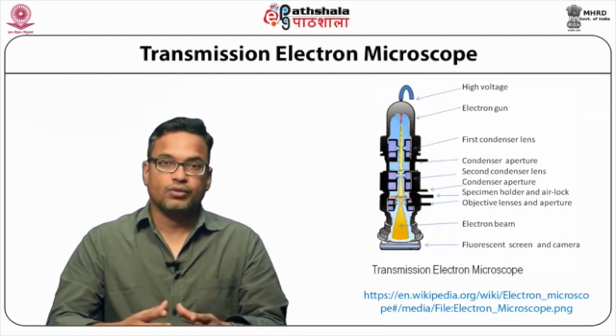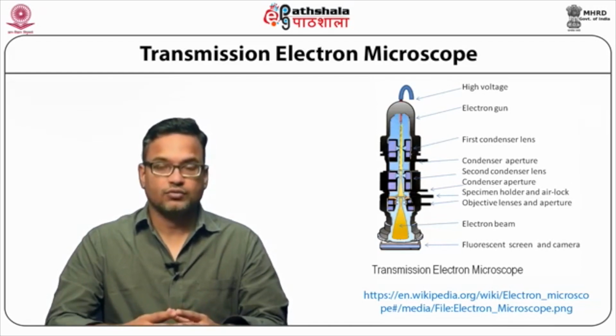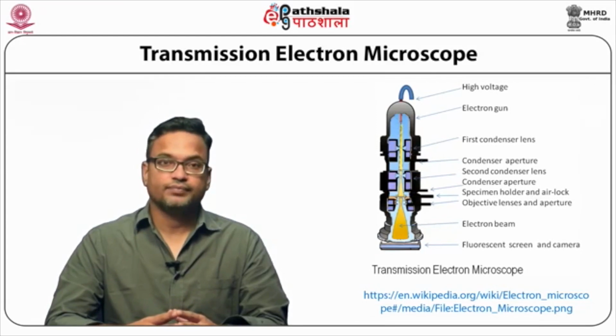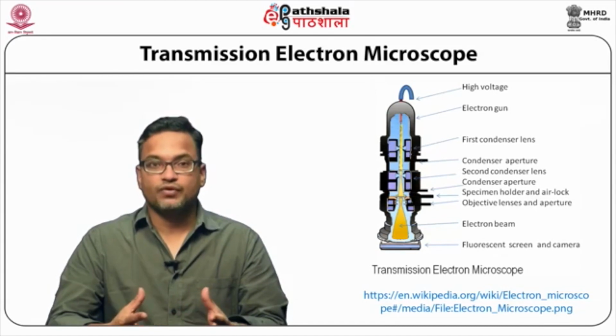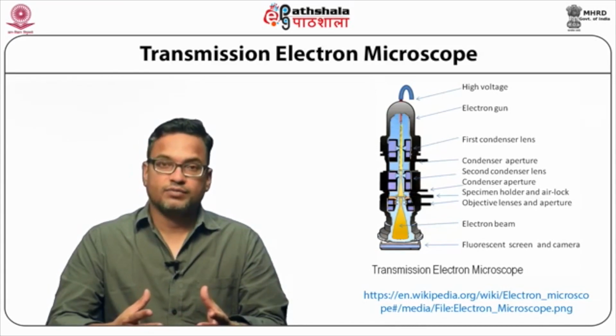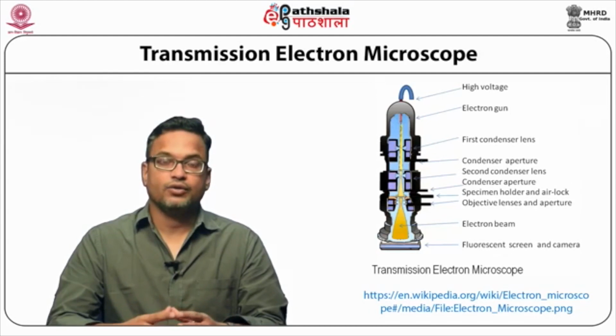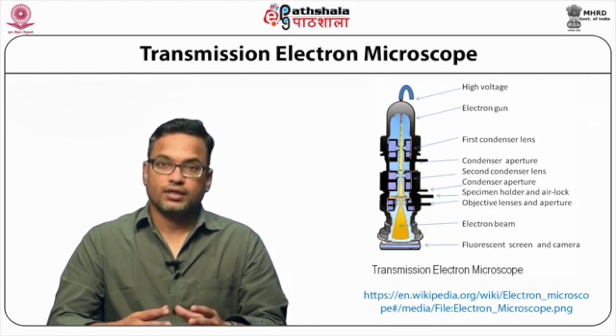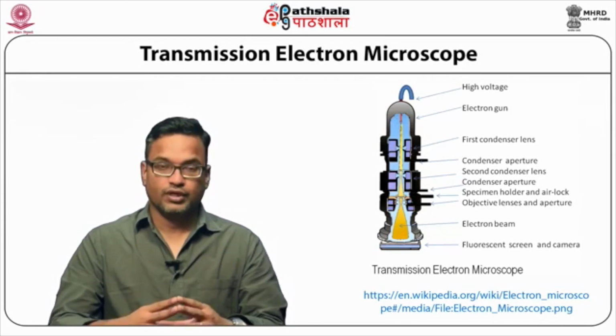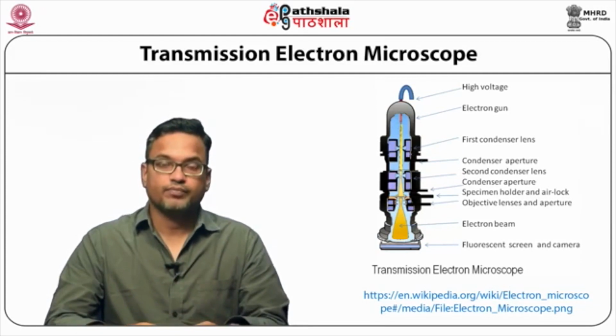Now using the anode, the beam is accelerated and directed toward the sample, and the sample has to be ultra thin. It has to be very thin, approximately 100 nanometers or even less, so that it can be illuminated and better viewed. The electron beam directed by the anode is further focused by the electrostatic or electromagnetic lens, which allows it to be directed onto the sample.